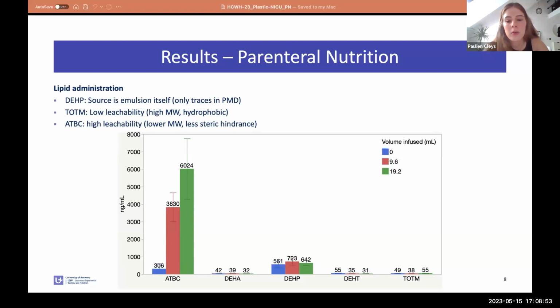And this is also confirmed in our study, where we see virtually no concentrations of TOTM in the non-lipid samples, despite it being a plasticizer which was highly abundant in the plastic medical devices which were used for the administration. And although the concentrations were quite low in the plastic medical devices used for lipid administration, we see very low concentrations during the migration study, so very low concentrations in the lipid samples during administration of the parenteral nutrition. So I think this was the main characteristics of this slide.